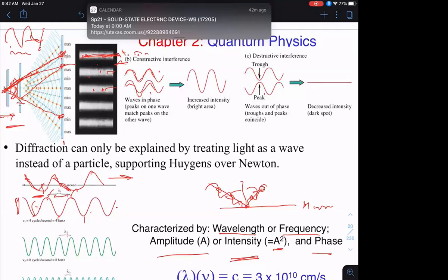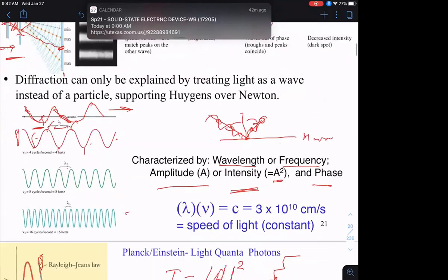corresponding to a wave property, and this is the de Broglie wave characteristic of the electron. Now, the way the experiment is done in the case of electrons is you don't really shine an electron through a screen like so. You shine it through a crystal, because remember, a crystal has a periodic structure. So when I shine this electron wave through a periodic arrangement of atoms in the crystal, the electrons undergo diffraction phenomena.